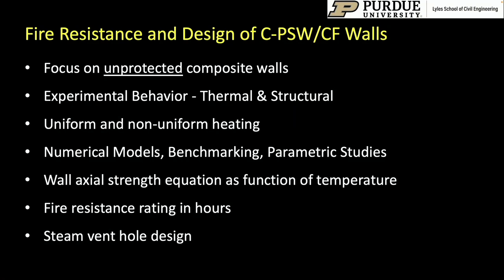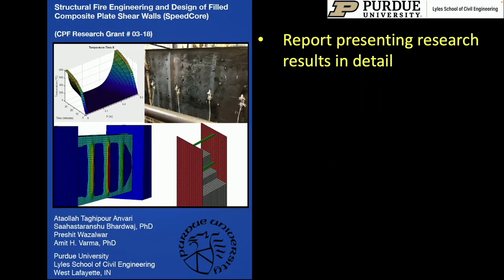So that's where we focused on. We conducted experimental tests, which included looking at the thermal behavior and the structural behavior to both uniform and non-uniform heating. And we developed numerical models that were benchmarked to the experimental data and then used to conduct parametric studies. At the end, we were able to develop wall axial strength equations as a function of temperature and fire resistance rating in hours for the system, and also provide recommendations for steam vent holes for the system.